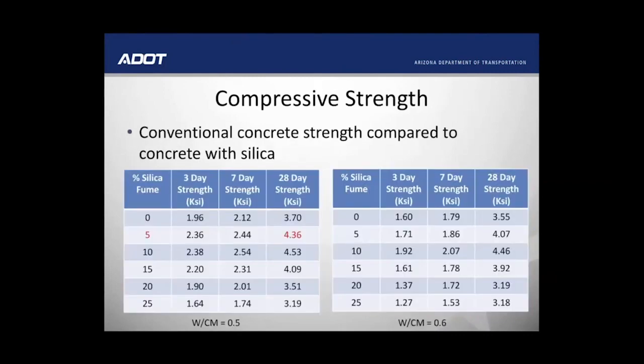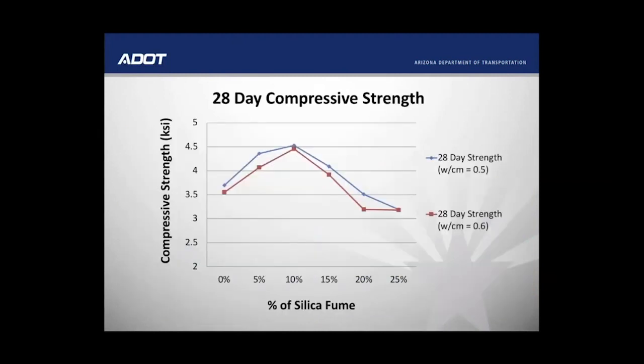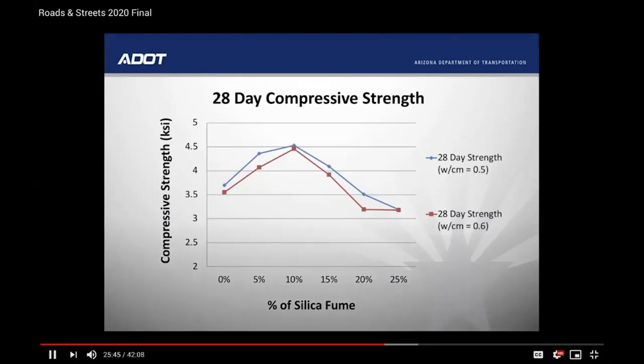Okay, back to some of the benefits of silica fume. So here is reference information for the effect of silica fume on compressive strength of concrete. Remember, ADOT typically uses about 4 to 5% silica fume at a water-cement ratio of 0.45 or less. These numbers are for concrete that does not include fly ash and is at higher water-cement ratios. We can see that between 5% and 10% silica fume will provide the greatest increase in compressive strength, and the higher water-cement ratio results in slightly reduced strength.